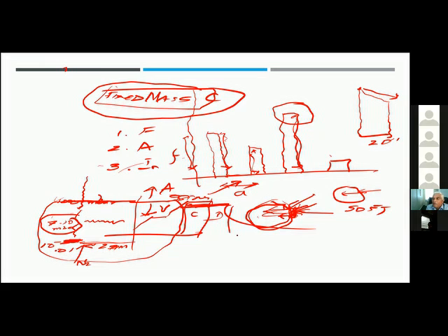The system is under vacuum, which means what? It is under an external pressure of 1 bar. It's not under any internal pressure, except when it goes into the quench chamber and you're doing gas quenching. Quenching itself is about 30 to 40 seconds. If at all it is in a pressure mode, it is only for 30 to 40 seconds, and that too in a cold cell. The heated furnace is always under external pressure of 1 bar. And if anything happens, it will implode. Not that anything has ever imploded, because you never get scared of a 1 bar pressure differential. Even a thermos flask at home has a 1 bar pressure. So there is no safety issue here.